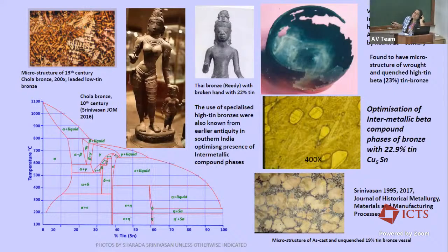But astonishingly, in South India, it's not as if they didn't know what to do with bronze and what happens with higher compositions and how to manipulate. And fascinatingly, they were using a particular composition of bronze at about 23% tin, where if you look at this phase diagram, which shows you what keeps happening when you keep alloying tin to copper at different temperatures. So at 23% tin bronze, you find that at a high temperature of about 650 to 750 degrees, there is a formation of this beta phase. And this beta phase is actually an intermetallic compound of composition Cu5Sn, and a fixed composition of 22.9% tin. So what happens is that when you have a bronze which optimizes this composition of the beta phase, then if you heat it to very high temperatures, you can actually forge that bronze very extensively.